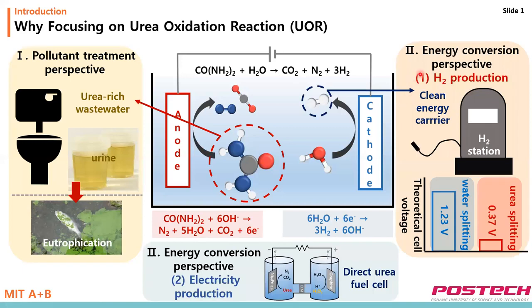Second perspective relates to energy conversion. In an electrochemical system, hydrogen evolution reaction occurs at the cathode side. This electrochemically produced hydrogen acts as a clean energy carrier. So there is a thermodynamic advantage of using the UOR at the anode instead of oxygen evolution reaction. Comparing thermodynamic cell voltage, using the urea splitting is recommended.